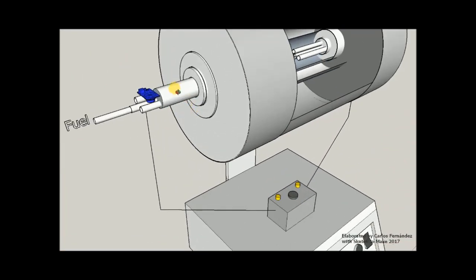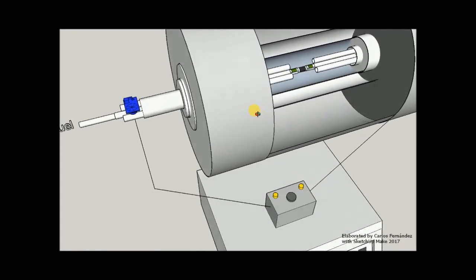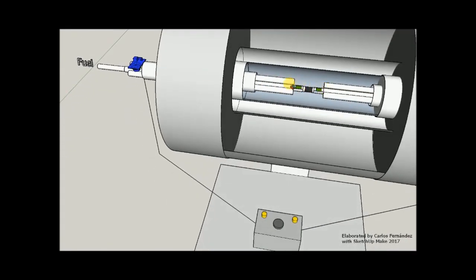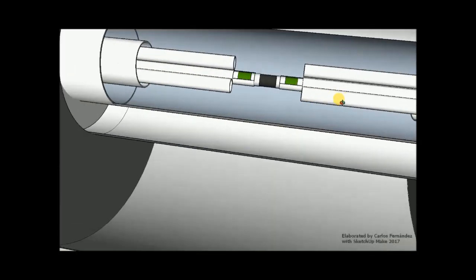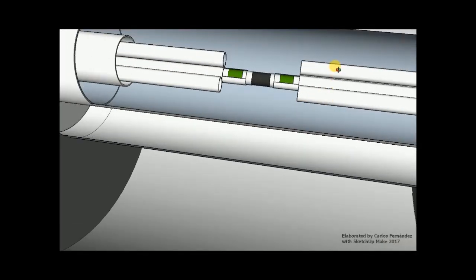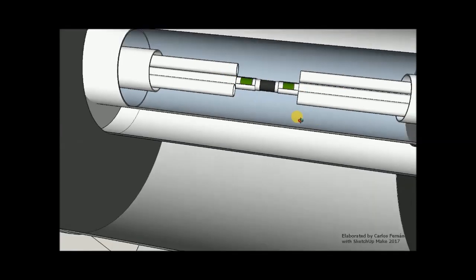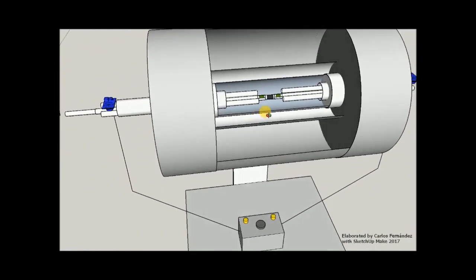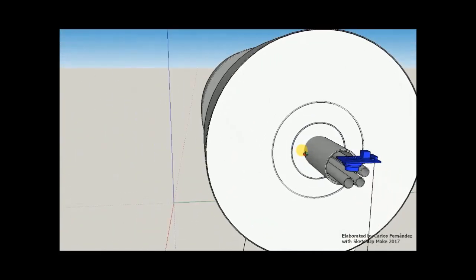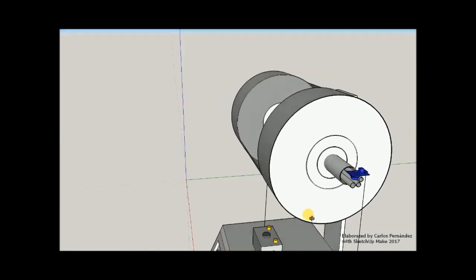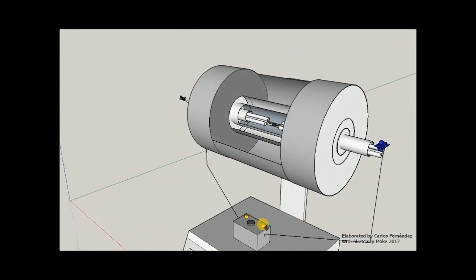The furnace has a quartz tube where the microtubular solid oxide fuel cell prototypes are placed. Samples are connected to alumina tubes to let the fuel in. Of these three tubes, the one located at the center is for flowing the hydrogen, while the other two are for supporting the sample. Each gas sensor, showing dark blue here, was placed close to an end of the quartz tube. And the box containing the RGB LEDs, the buzzer, and the Arduino board was located at the center of the experimental setup.